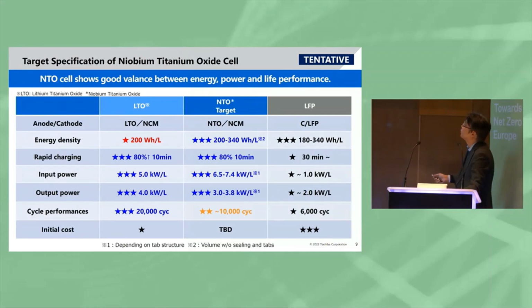This table compares the performances of each battery chemistry. This data is based on some experimental data. At this point, the energy density of the NTO battery can improve by approximately 1.5 times that of the LTO batteries, and it is equal to, sometimes higher than, that of the LFP carbon chemistry. And the NTO battery can inherit the rapid charging, input power, and output power performance from the LTO. Unfortunately, the cycle performance is slightly less good than that of the LTO, but we think it is still high enough compared to the LFP in any of the applications.